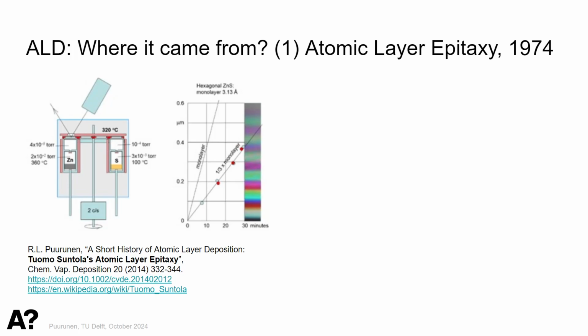He had calculated in advance that if you get one monolayer per cycle, like they thought you would, you should get a purple reflection from the glass after a certain time, because they did 2 cycles per second. The first experiment was made, and they were expecting something and getting something else. Growth happened, the experiment was successful, but they didn't get as thick a film as they thought, only about 1/3 of it, and they were disappointed.